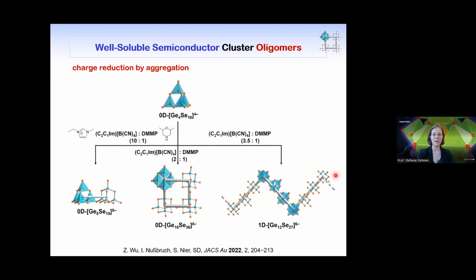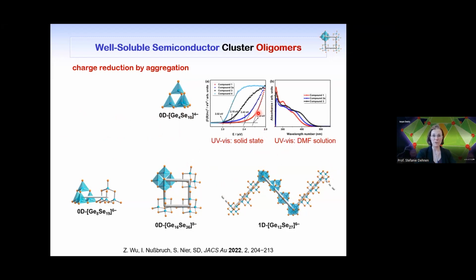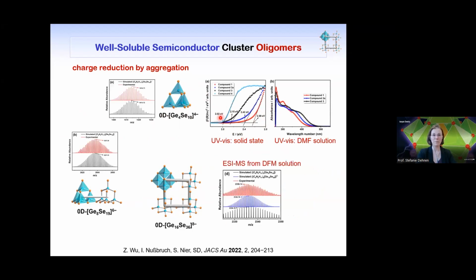First, the solubility, and also the optical properties. For the 3 molecular ones, we can see that the optical properties undergo a shift as expected with increasing cluster size. It's redshifted, and we see roughly the same behavior also for the solid state, including, of course, the zigzag chain, which has the smallest band gap. You can see by mass spectrometry that you really have soluble clusters here. This, by the way, is the largest binary chalcogenidometalate cluster, and it's soluble. So this was pretty nice to recognize.